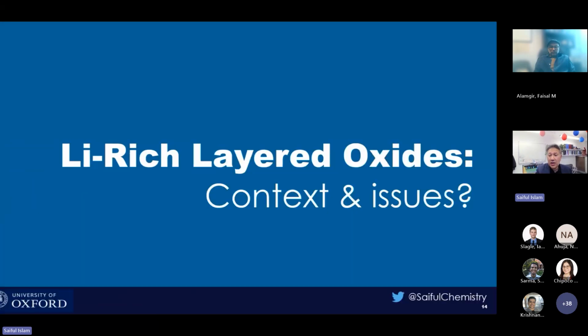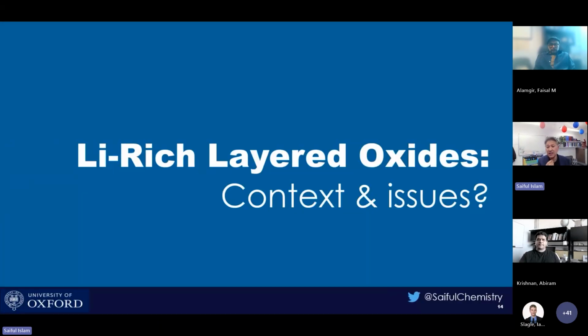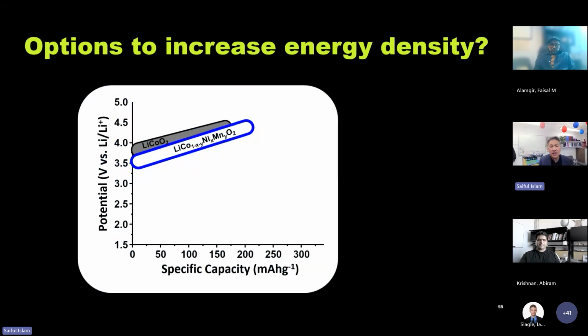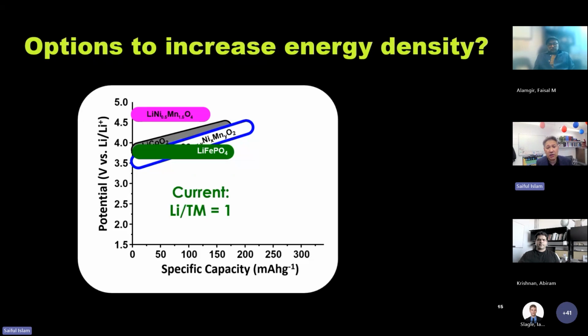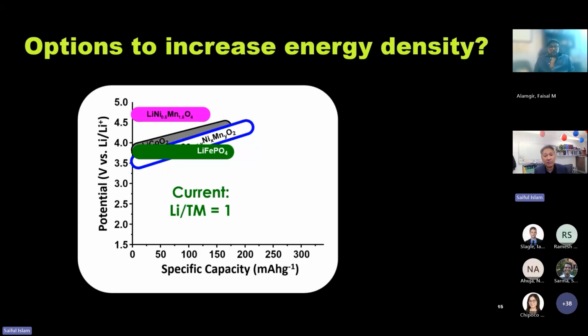What about new work? So we're looking now at lithium-rich layered oxides. And so let me give you some background to these lithium-rich materials. So what I'm showing you here is the potential up the y-axis and the specific capacity in milliampere hours per gram along the x-axis. I'm showing you some conventional materials, lithium cobalt oxide and NMC, which reaches just over 200 milliampere hours per gram on the material side. And then lithium iron phosphate and the lithium nickel manganese spinel in green and purple respectively.